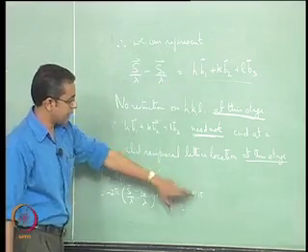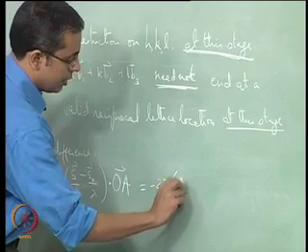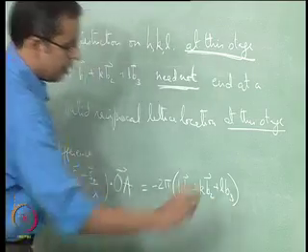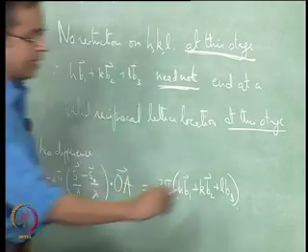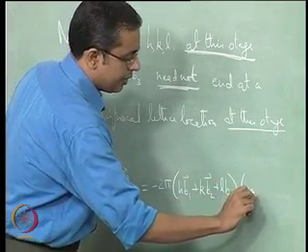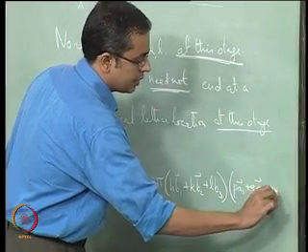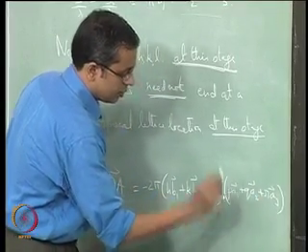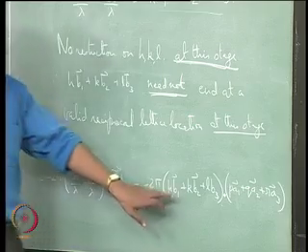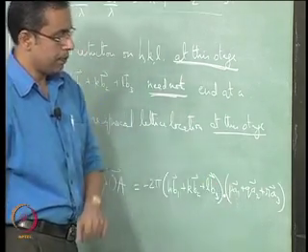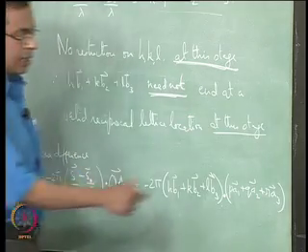So therefore we can write that as the vector hb1 plus kb2 plus lb3, and OA we have already defined as PA1 plus QA2 plus RA3, and this is a dot product, a dot product of HB1 KB2 LB3 with PA1 QA2 RA3, where P, Q and R have